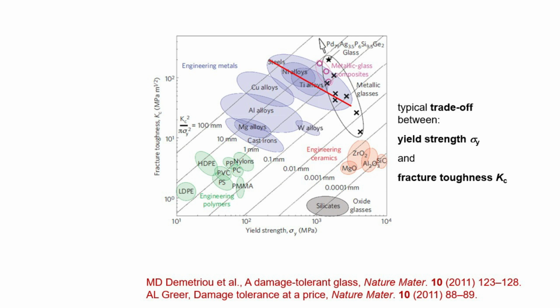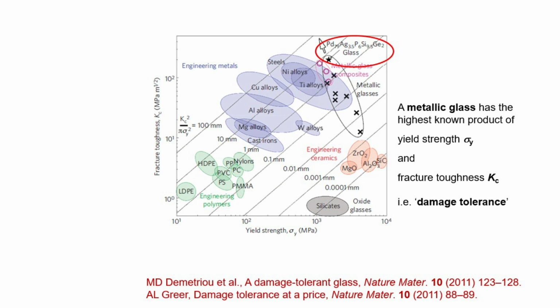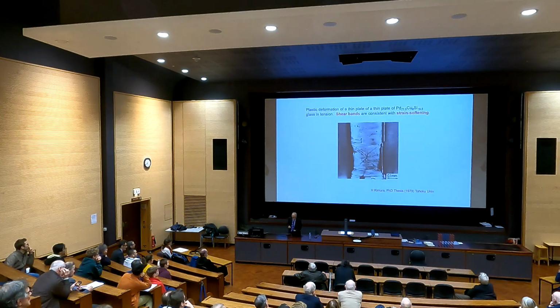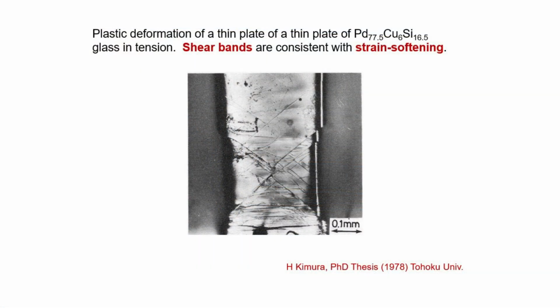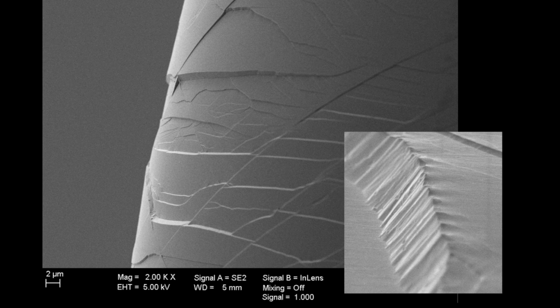Interestingly, if you say, well, can you tell me of all known materials, which has the best, highest combination or highest product of the two things, yield stress and toughness, it is in fact a metallic glass. And that's the property we could call damage tolerance. So we do not need to worry about them cracking in the way you just saw. There is still a problem, though, that when you deform them, they don't deform smoothly. They look like this. It's telling us that unlike our crystalline metals, the flow is now localizing. It's not delocalizing. So this is work or strain softening, not strain hardening. And that's desperately bad news.